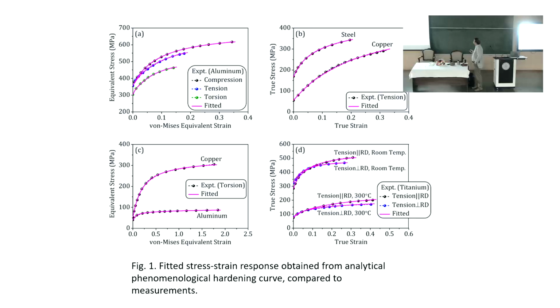Here this is for steel, for copper, again tension, and here is torsion for larger strain, because here strain is limited - tensile testing is limited, but torsion you can reach higher strains. So here we go up to about 2 for Mises equivalent strain, and you see even for that large strain we still get perfect agreement.